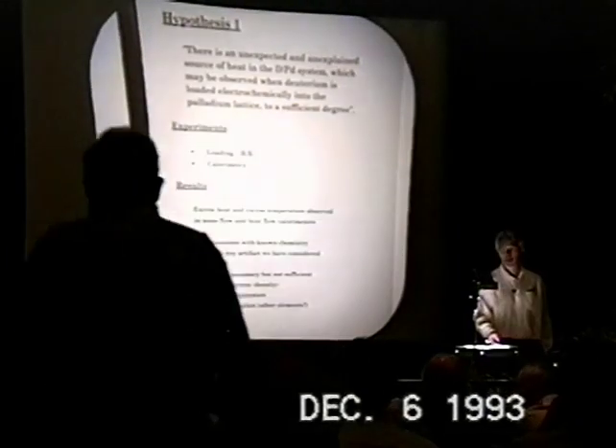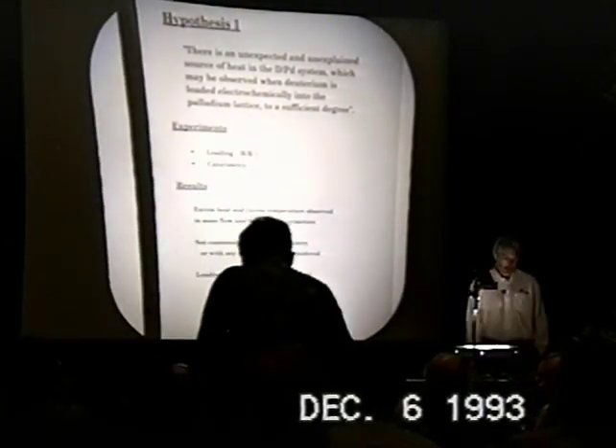We find that loading is indeed necessary, but it is not a sufficient condition for the observation of excess power. The current is important, or the current density, or the electrochemical potential of the deuteron in the lattice, related properties. Temperature is certainly important, and not an orthogonal variable, as Katie pointed out this morning. There seems also to be some time-dependent process, so that one must establish a loading, maintain a loading, and probably also maintain that loading at high current densities for a significant time before one expects to observe any anomalous heat source.